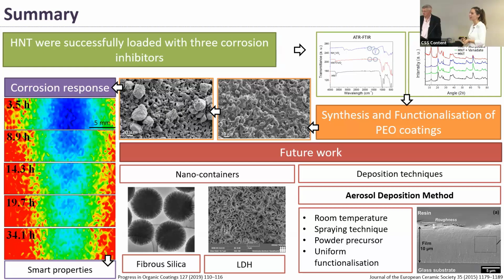Okay, thank you. And in terms of the nanotubes, do you have any control over the size of the pores within them? Right now I use them like they are. So these are natural clays, but there are mechanisms where you can enlarge the lumen of the nanotube. If you do an acidic treatment, you can possibly enlarge the loading capacity. At this stage, I'm not that worried about the loading capacity, because I can see that the loading capacity is sufficient to have a significant impact on the self-healing properties. But yes, it's a possibility. It's something that has been done, and many people do it quite often. Great. Okay, thank you very much.